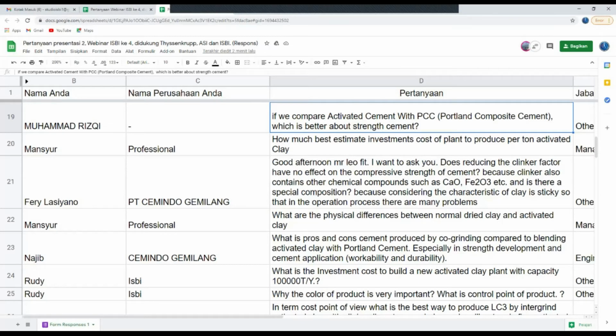Okay, so here's the question on whether reducing the clinker factor has an effect on the compressive strength of cement. So yes, for sure, this is normally the case. If you just talk about using standard fillers like limestone, then a reduced clinker content will lead to drastically decreased compressive strength. That's absolutely correct. If we talk about activated clay, you all know that this is an active component. So this is reacting with limestone and clinker together. And this is giving some strength advantages.